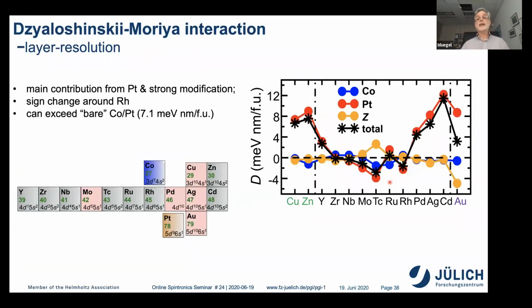And we can also calculate the Dzyaloshinskii-Moriya interaction. And I would like to point out the following. These black stars here, this is the total contribution to the Dzyaloshinskii-Moriya interaction. It's large at the beginning, it's large at the end, it's small in the center. And here we analyze the contributions to this quantity. You see the most important contribution is the platinum. The platinum contribution follows the total contribution very well.